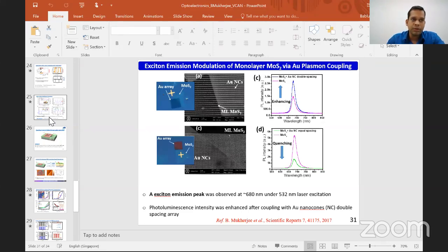There may be some reason that it has good optical absorption, and we also need to think about how the carriers get collected in the electrodes in the device structure. We basically give electrical contacts on top of this flake. So not only absorption, we need to see how photogenerated carriers are getting collected at the top electrodes. If there is a distribution of photogenerated carriers across the thickness, that sometimes gives inhomogeneity, or sometimes they get lost and cannot contribute to the device performance. So there needs to be further study in detail on how thickness can affect this optoelectronic device performance.